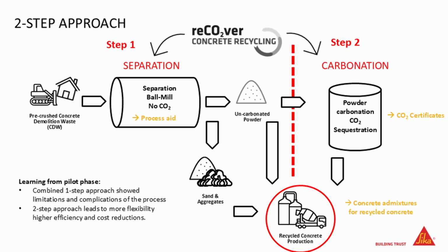Let's say we assume that the recycled concrete is more than 20 years old. So we assume that the cement phases are completely reacted. So this is then an inert material you can use as a filler material. But there are maybe other materials. The properties of that material, be it carbonated or uncarbonated, are more or less the same. That carbonation has no effect on some activity of that powder that was unfortunately not detected. That would be very nice if there would be some activity, but in fact it's not.